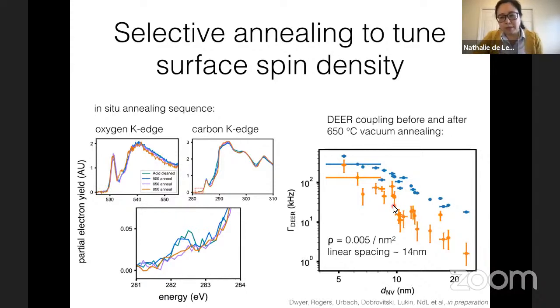It looks like we have some dangling bonds that are responsible for these surface spins, but we immediately saw one big puzzle in the data. So the first puzzle is that this scaling of DEER coupling with depth corresponds to a density of surface spins that is 0.005 per nanometer squared, which is a linear spacing of around 14 nanometers between surface spins. So that means that we're operating in a regime where the NV is much closer to these surface spins than the surface spins are to each other.